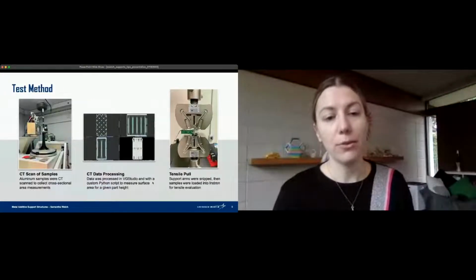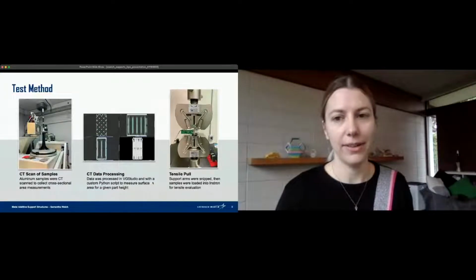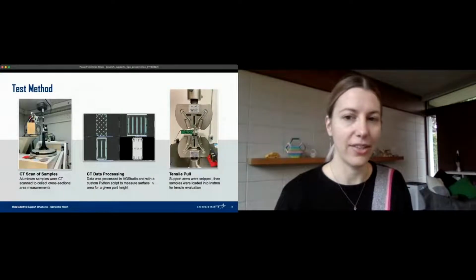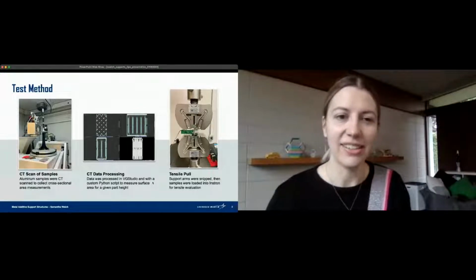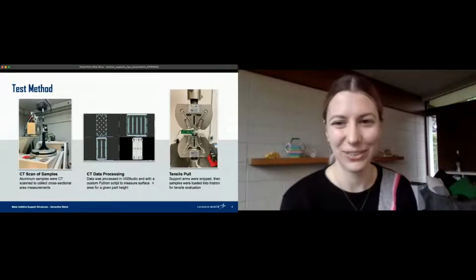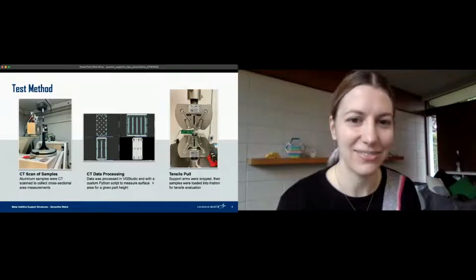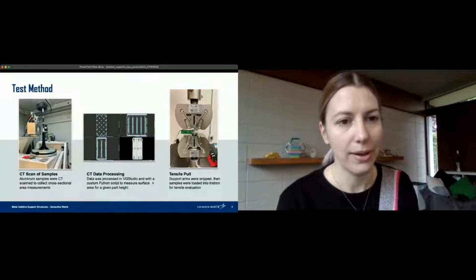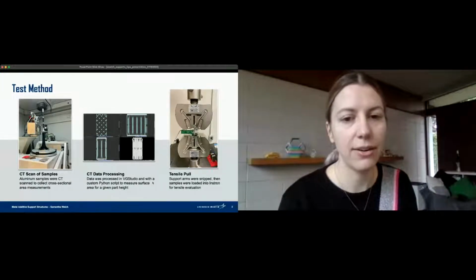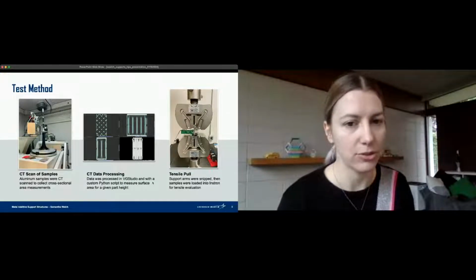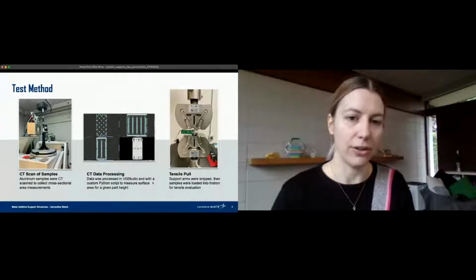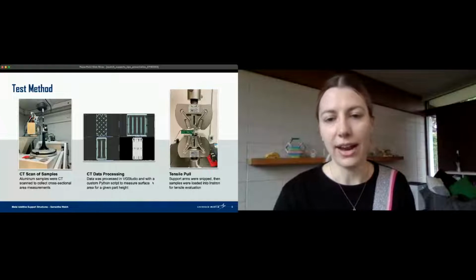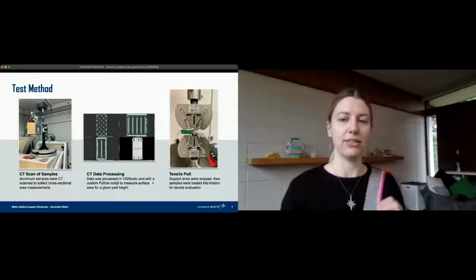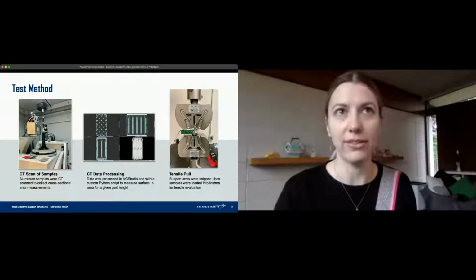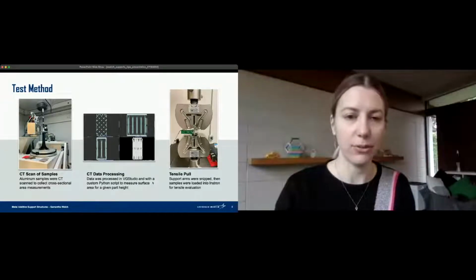So for the aluminum samples, I CT scanned them. If we're going to get tensile data out there, I need to know my cross-sectional area. And it's not quite as simple to measure as it is for a bulk material, with this fancy grid pattern. So all the aluminum samples were CT scanned. We had a modified Python script to extract the cross-sectional area as a function of height throughout the part. And then after that data was collected, the tensile pull was performed, as well as a removability evaluation afterwards.